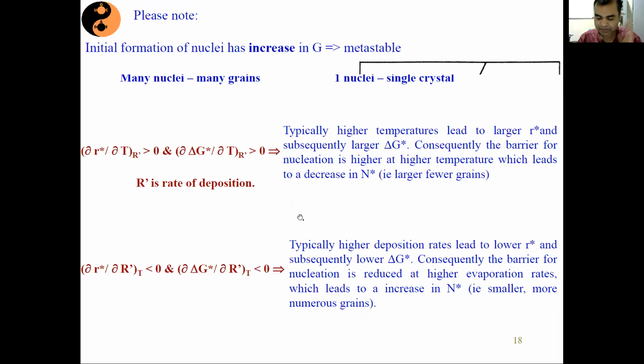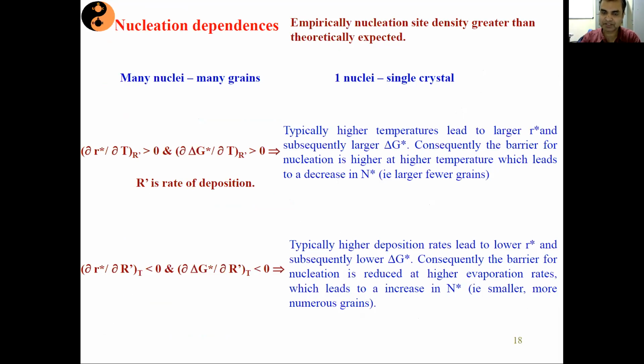So this is a very important thing to really understand, which nanoparticles are going to be stable. Okay. So if I increase the rate of deposition, or if I increase the temperature, then with increase in temperature, your energy barrier increases. Your energy barrier increases means what? You require a very high energy to make the nucleation stable. So that means you will have fewer nucleation sites, but larger in dimension. So those will give rise to a kind of larger grain size picture, and larger grain size means your system will have a lesser contribution from your grain boundaries.